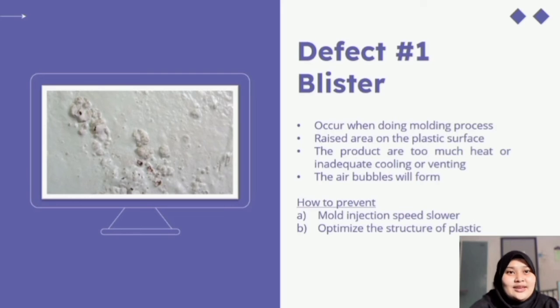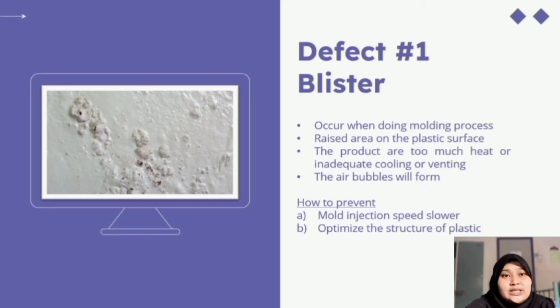Firstly, the blister defect. Blisters are an injection molding defect that present as a raised defect on the surface of a molded part. A blister is a raised area on the plastic surface. It is generally the product of too much heat on the tool or of inadequate cooling or venting. For instance, if the injector has a flow pattern issue, it might melt the resin at once, allowing air bubbles to enter the molten resin.